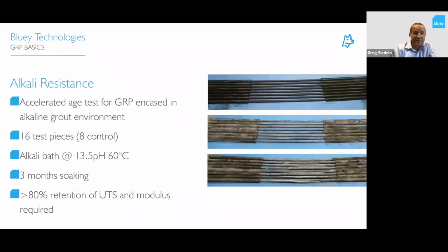So alkali resistance, this is another critical testing for the GRP. This is testing the durability and retained strength in an alkaline environment. Part of the standard is you have to test in an alkali bath at 13.5 pH at 60 degrees, and you've got to have it soaked for 3 months. The test standards say you've got to have greater than 80% retention of your UTS and your modulus to be classified as a Class A.